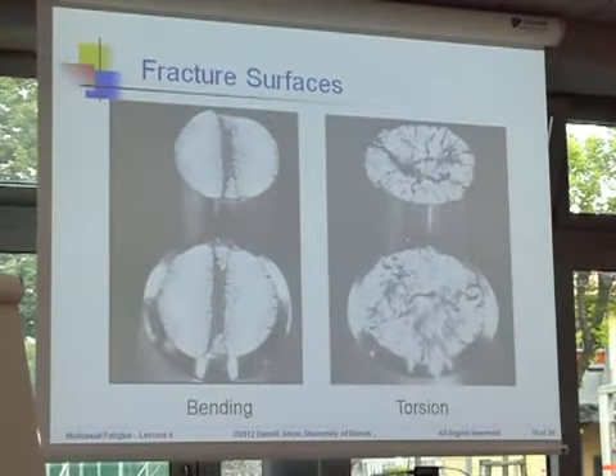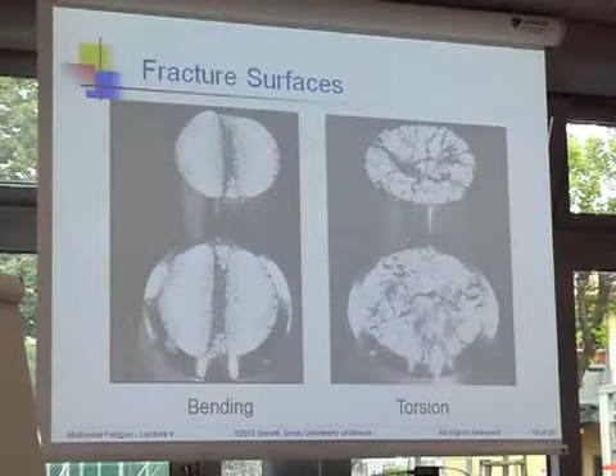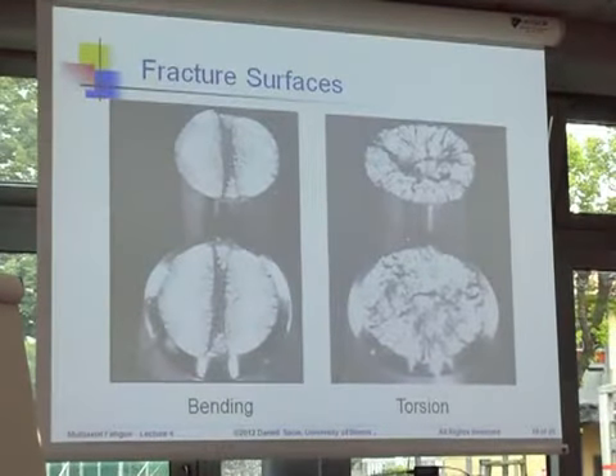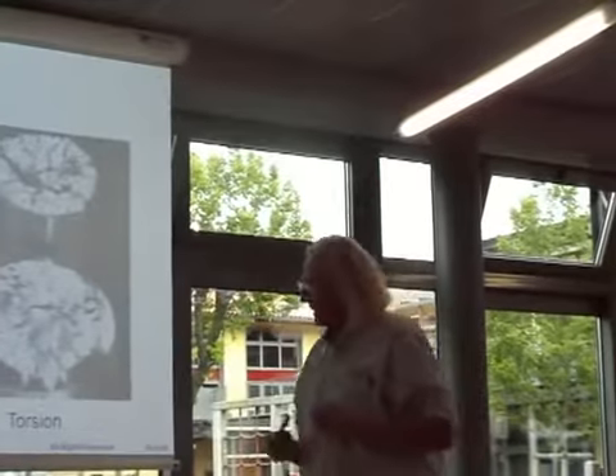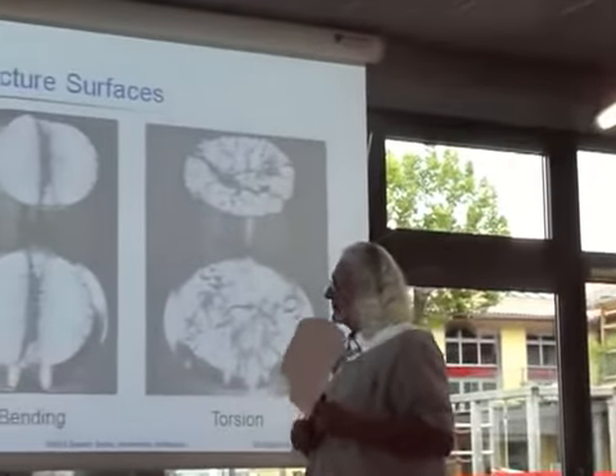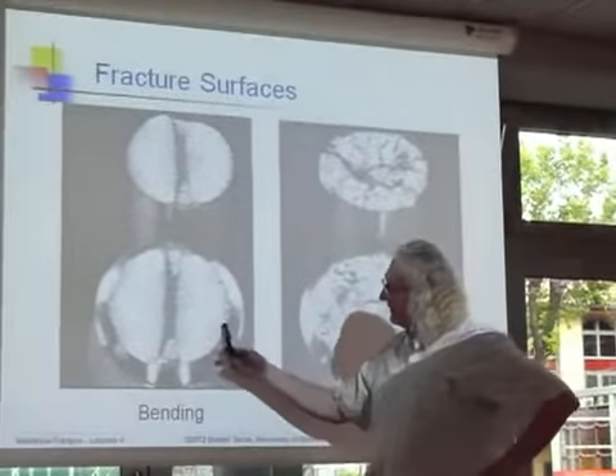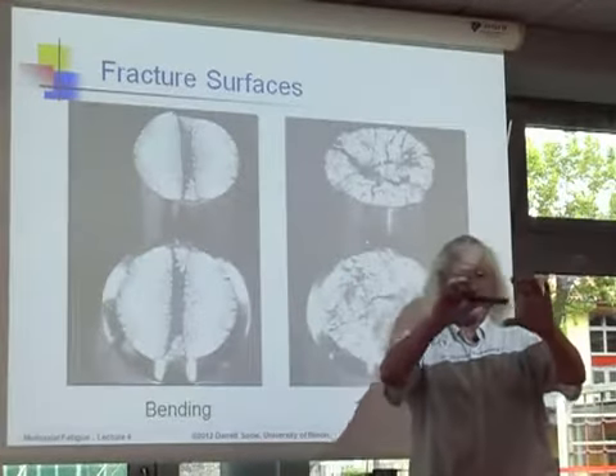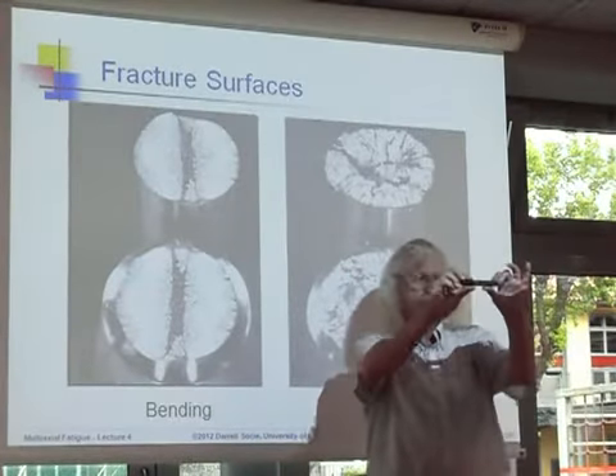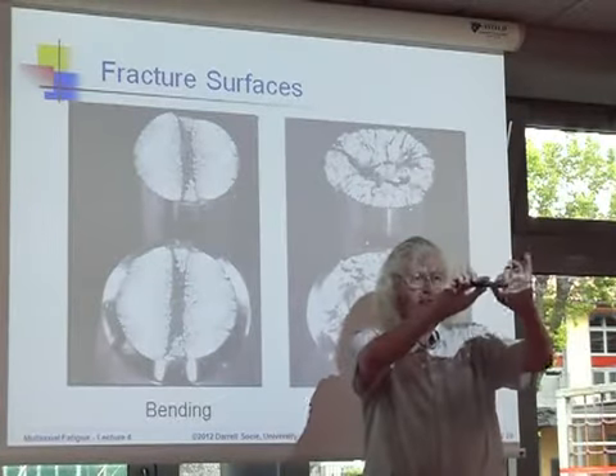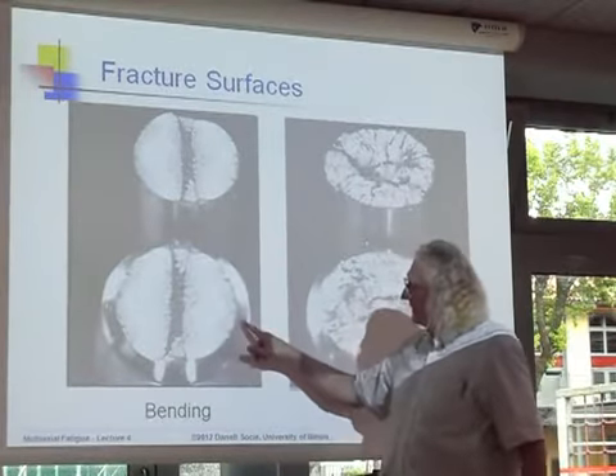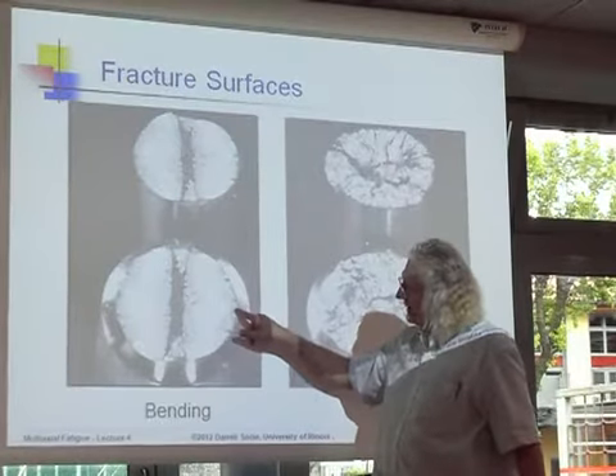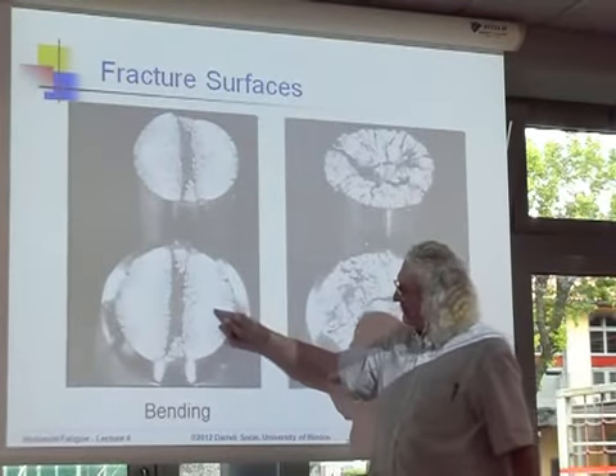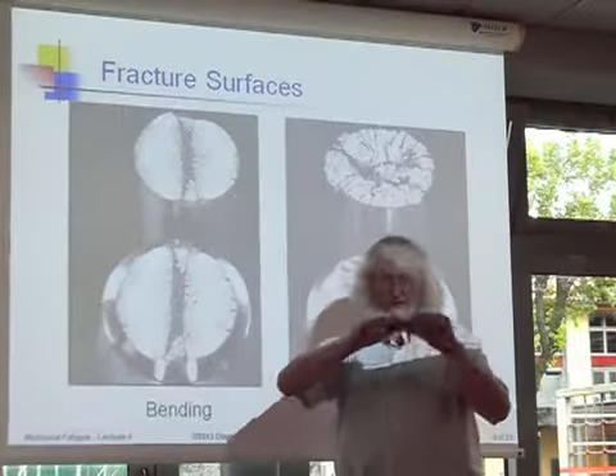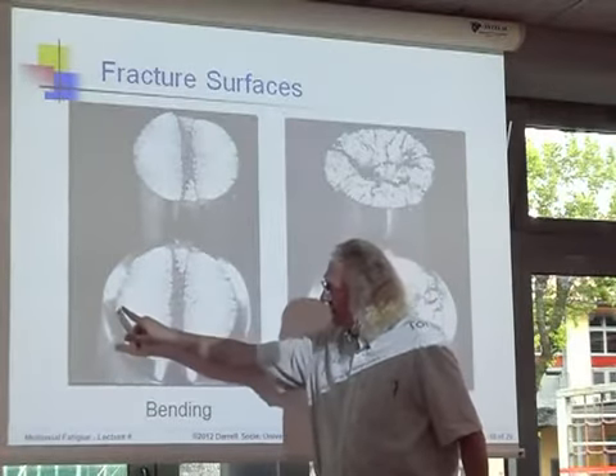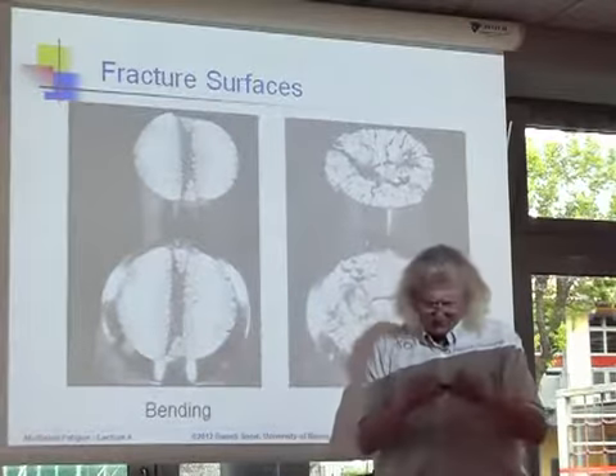So I just take a solid bar, and this is a bar in bending, right? I'm going to bend it back and forth like that, and I'll get some life, maybe a few 100,000 cycles. And this is what I see on the fracture surface. Of course, the crack will nucleate here, and this crack will grow towards the center, and because it's in reverse bending, a crack will nucleate here, and it will go through the center.